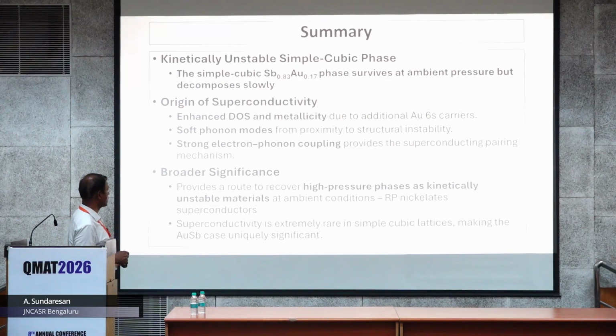The origin of superconductivity: you have the enhanced density of states and metallicity coming from the Au modified electronic structure. If you look at the average electrons, actually it should reduce it, but it modifies the electronic structure. Then you have the soft mode phonon coming from the boson peak evidence, and there seems to be a strong electron phonon coupling, which we are trying to further develop in theory.